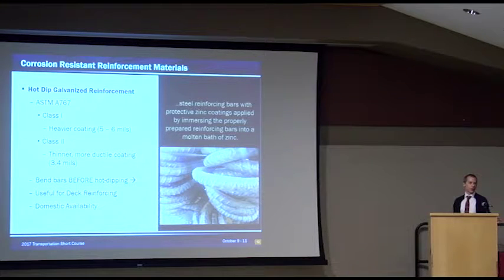Now, hot dip galvanized reinforcement. Hot dip galvanizing is basically dipping metal into a bath of molten zinc, and the zinc helps the material to fight corrosion. There's two classes of hot dip galvanizing for reinforcement. Class 1 and Class 2 listed up here. The thicker one is Class 1, and you might think, well, the thicker coating is going to be the stronger coating. But if you fabricate the bar after you've hot dipped it, and you're using that thicker coating, it might look something like this picture here. And I don't know if y'all can see the detail from the back, but there's a lot of chipping in that galvanized coating, and that's kind of defeating the purpose here.